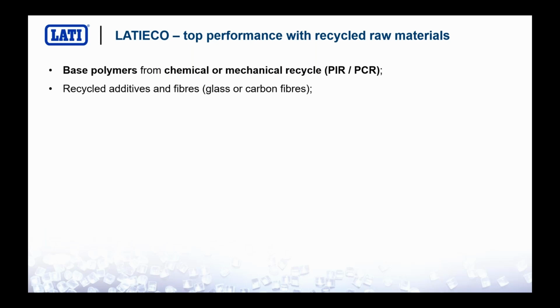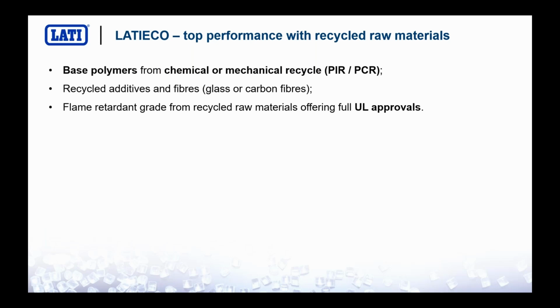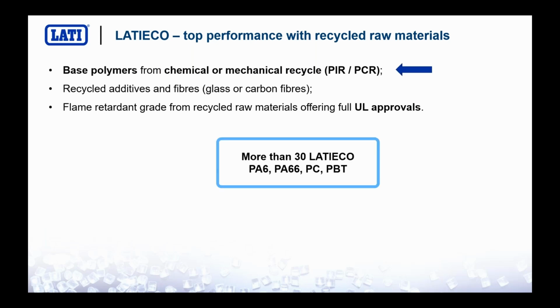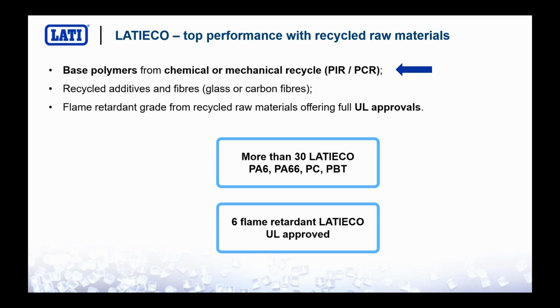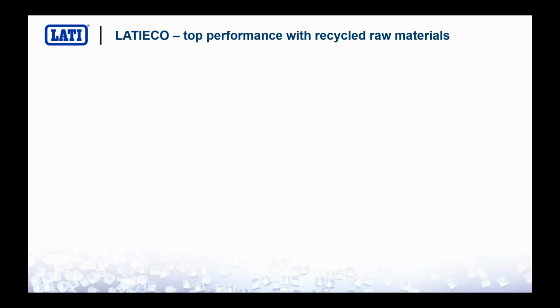Once we have new flame retardant grades obtained from recycled polymers, we want them to be fully approved by the UL lab in order to have new, reliable, certified, approved flame retardant products. Nowadays, we have more than 30 LATI Eco flame retardant and non-flame retardant products already available, and 6 are already UL approved. Of course, it's very important not only to have recycled raw materials in new compounds, but to have them properly compounded and to be sure that they are actually performing the way we want them to.